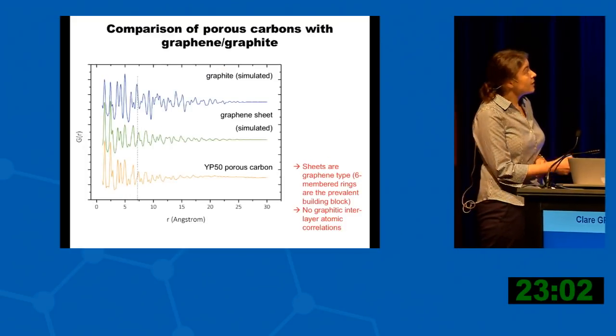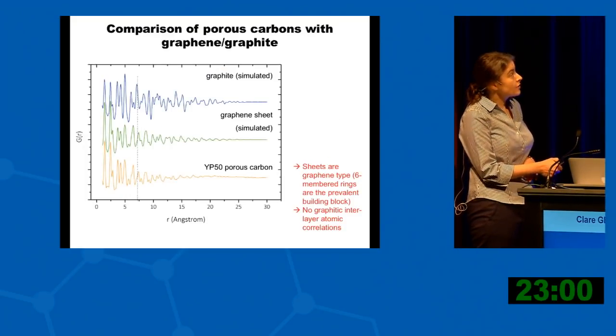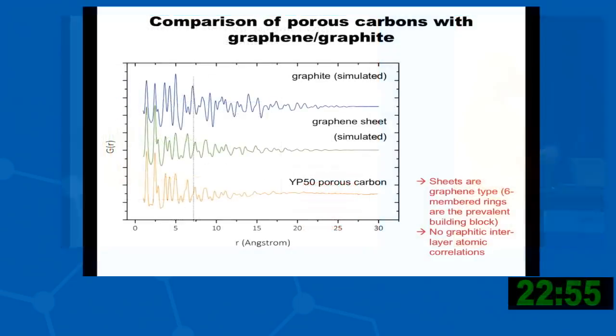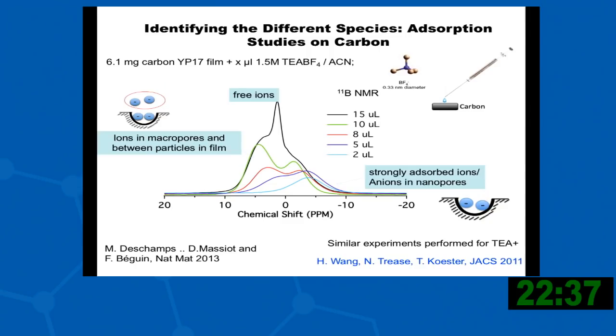And so if you just compare a typical porous carbon with simulations of graphene and graphite, you can see that the correlations are very, very similar, but you're missing the correlations that would come from the stacking of the carbon sheets. And so these systems are largely based on curved graphene sheets. And each of these wiggles are real, these are not noise, and they tell you about the nature of the structure. So what about the NMR of these types of systems?